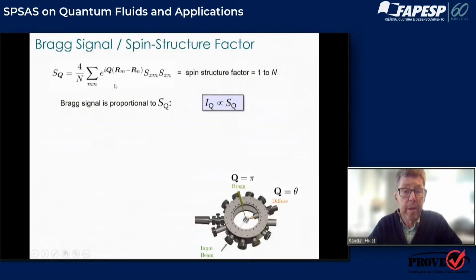So that function is called the spin structure factor. This is the static structure factor. It's for elastic scattering. Q is the Bragg wave vector. And we're looking to see a non-zero value of this correlation function, which occurs once you get close to the Néel temperature and antiferromagnetic order is supposed to develop. So it turns out the Bragg signal is proportional to this static structure factor. And you can measure the fraction of light which is scattered back into this camera. You can determine what the correlations are in this system.